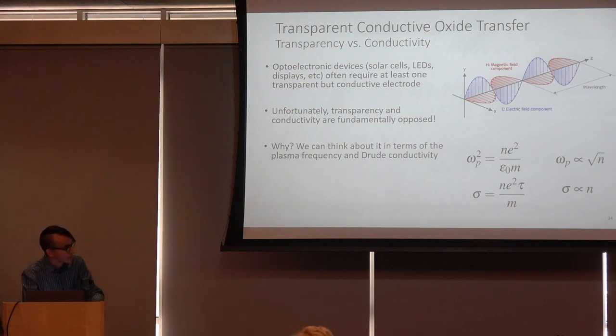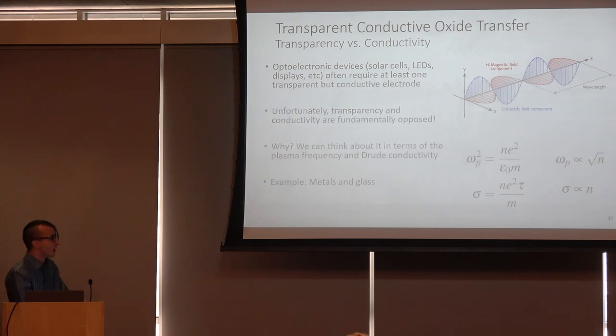The key thing that I want to highlight is that the plasma frequency is proportional to the square root of the carrier density, and the conductivity is proportional to the carrier density. And so basically, as we increase the carrier density in our material, we are going to be making it less transparent but more conductive. And so there's this trade-off that we fundamentally have to balance out. An easy example to think about would just be like metals and glass. Metals, very conductive, not transparent. Glass, very transparent, not conductive.